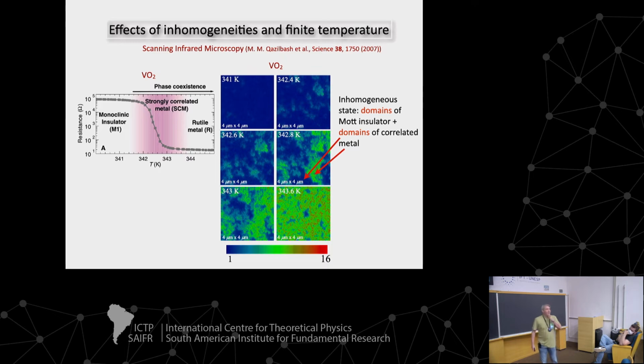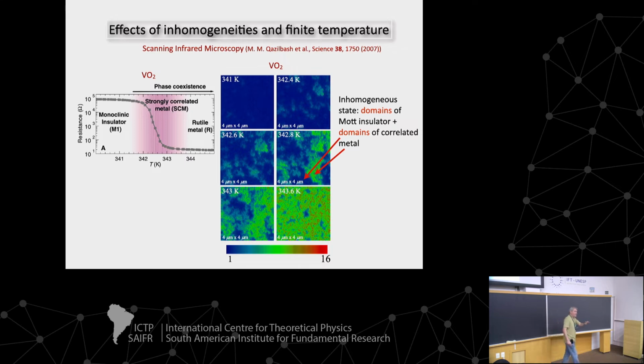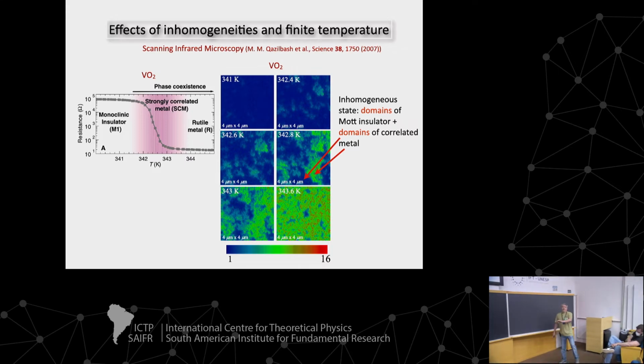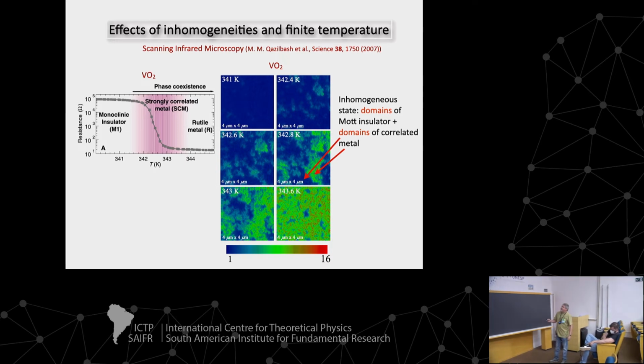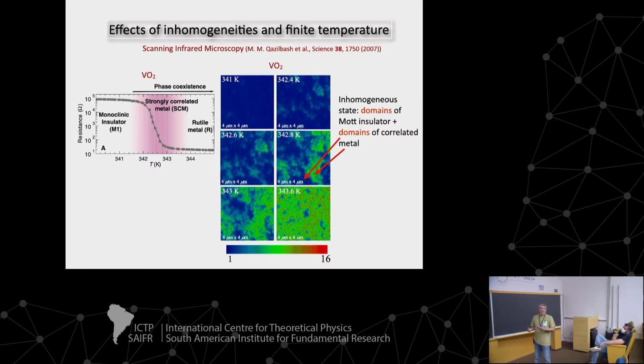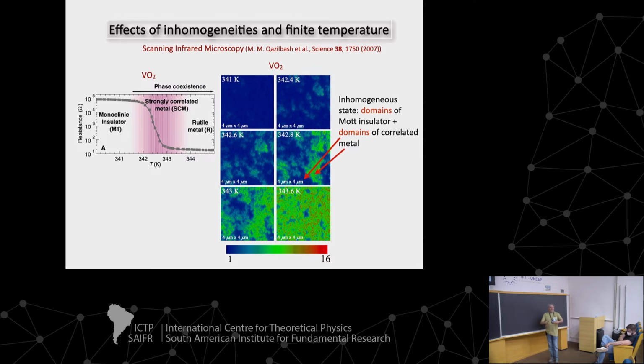Now, what I want to talk about is not the clean system. So this is another one of those paradigmatic systems where you have a Mott transition, VO2. And this is scanning infrared microscopy data on VO2, which is basically a way of measuring locally the conductivity at small regions of your sample. And as you can see here, as you change the temperature and across the phase transition, you see very clearly that there are bubbles of metal and insulator that coexist with each other.